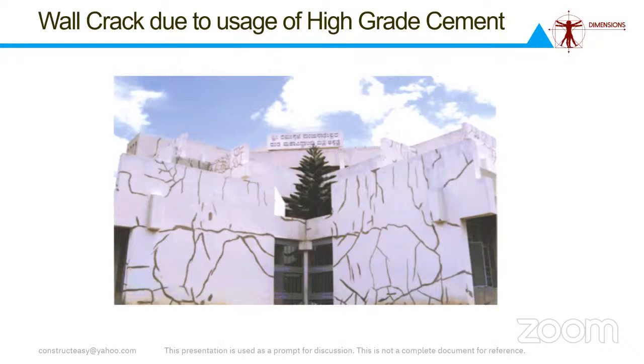Remember, the strength of cement doesn't always result in the strength of concrete. Strength of cement and strength of concrete need not be directly proportional. You can produce a very poor quality concrete with a very high quality cement. Very high grade cement can result in very poor grade concrete also. The mix design itself is an art with science as its basis. So this defect happened because they used a very high grade cement for plastering. They used OPC for plastering.